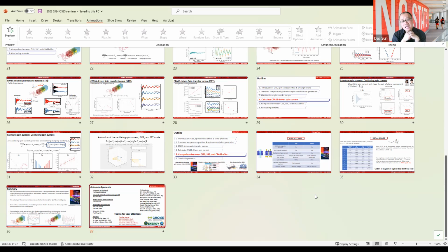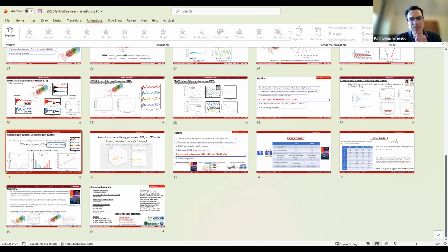Yes, we don't know why, because we were not able to directly measure the SX or SY component with our current setup. The SX and SY components are derived from the calculation for the STT signal. If you consider two oscillations with cosine omega t, both in X and Y forming the same phase, the fitting for one component is not reliable. That's why we have a very high error bar for SY. Basically it may be just one S rotating with cosine omega t, but the SY is not phase different. That's what we observed.